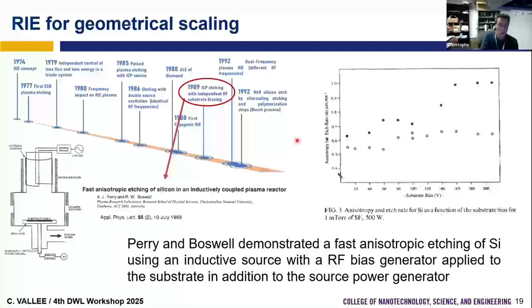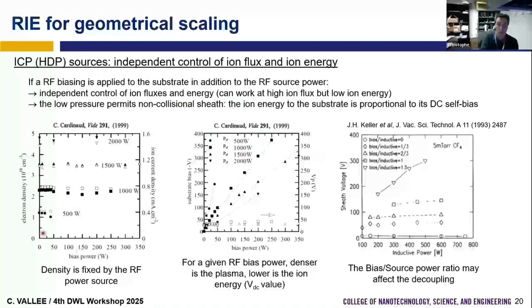So the idea is that if I go back to this device, the power applied to the coil, what we call the power source, will fix the plasma density, so you will fix the ion flux. And with the power applied to the substrate, you will not modify the flux, but you will modify the DC self bias, the ion energy. So you have a power bias to control the ion energy and a power source to control the ion flux. Now you can increase the ion flux without increasing the ion energy by playing, for example, with only the power source, or you can increase the ion energy without increasing the ion flux by playing with the bias power. So you have an independent control. This is what is illustrated here with this extract from this paper.